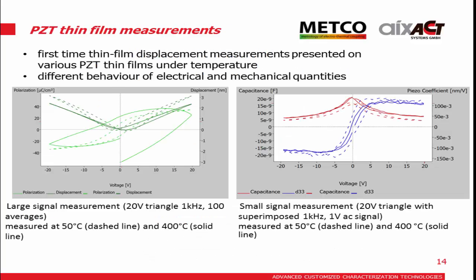So this is the first results we did on PZT thin films, and what you can nicely see is the dashed line here is the normal electrical hysteresis at room temperature, and this is the butterfly loop.